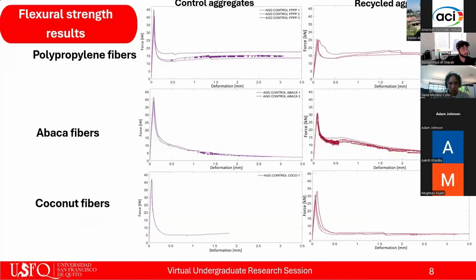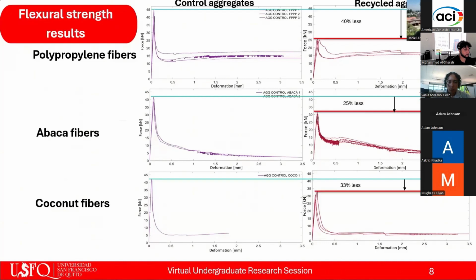We performed 3-point bending tests to measure peak flexural strength, post-cracking behavior, stiffness, and energy absorption of the fiber reinforced mixes. In terms of ductility after cracking, all beams meet the minimum deformation required, the standard about 0.14 inches, except the one with coconut fiber and natural aggregates, which reached only 0.07 inches, roughly half of the required value. This confirms that the proper addition of fiber significantly enhances post-cracking ductility. For peak load, mixes with recycled aggregates and natural fibers showed reductions of about 2/5, 1/4, and 1/3 compared to the control mix with polypropylene fibers and normal aggregates.